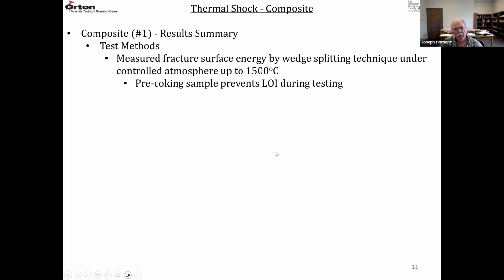So I just showed you this test method, the wedge splitting technique, how it can be used at elevated temperatures for these carbon-based materials. So they measure fracture surface energy by wedge splitting under controlled atmosphere up to 1500 degrees C. And we talked a little bit about the pyrolysis of the phenolic resin. Well, if you pre-coke the sample, you can pyrolyze the resin and then you won't have any loss on ignition during the testing. So you can do the same type of testing for a work of fracture, the chevron notch type sample, but you're also going to need a furnace with a controlled environment.